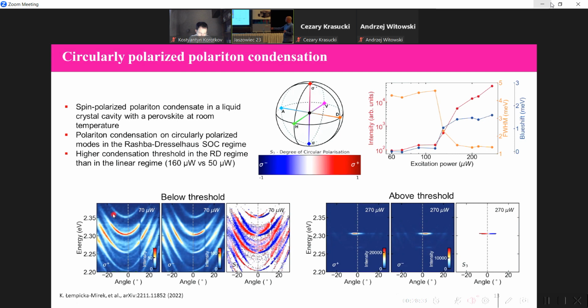Below threshold, we've got maps in sigma plus and sigma minus polarization, and here the degree of circular polarization. You can clearly see this is below the threshold, and above the threshold, there are two condensates, sigma plus and sigma minus, with sigma plus and sigma minus polarization.